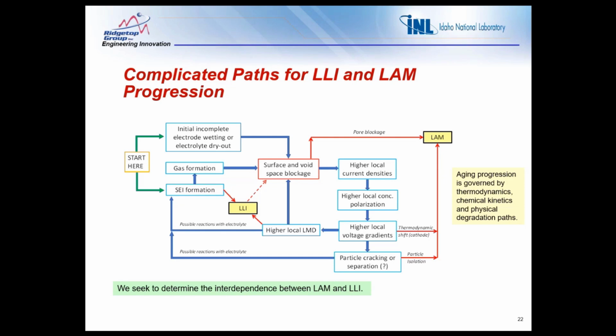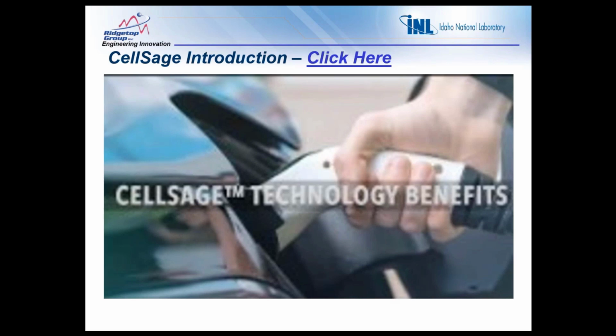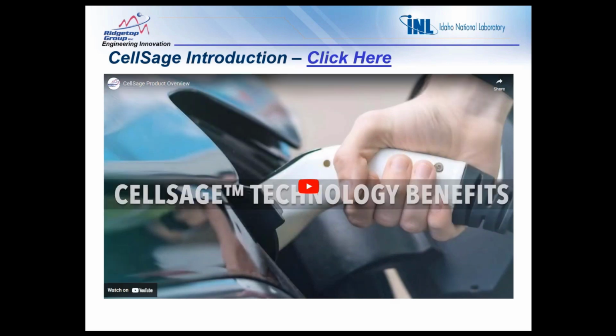Several processes such as SEI formation, gas formation, and the incomplete electrode wetting or electrolyte dryout can cause things such as surface and void space blockage, which have direct impacts on LLI and LAM with pore blockage. And then it also leads to higher local current densities and other key activities such as particle cracking or separation. So to address these failure modes and activities, we've developed our CellSage battery health modeling and simulation software through our original research and development work done with Dr. Kevin Gearing at INL. Here we have a brief overview of that technology.